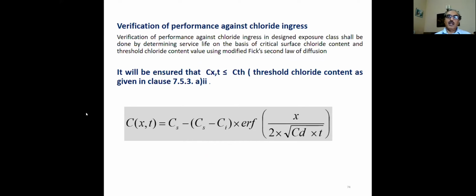Then, doing some regression analysis, we see what is the concentration at X, the cover depth, and time. At that time, this is the initial surface chloride. Based on that, we try to determine the time taken, T value, for different T values, to initiate the corrosion from this equation.